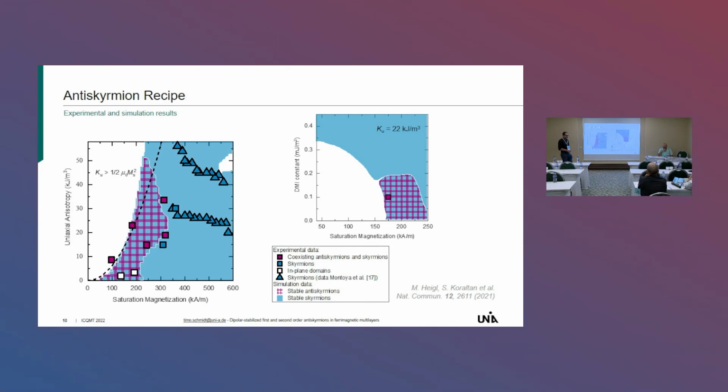We thought that it would introduce more DMI, but it effectively reduces the saturation magnetization, which was also a point for getting into that phase pocket, like Montoya et al.